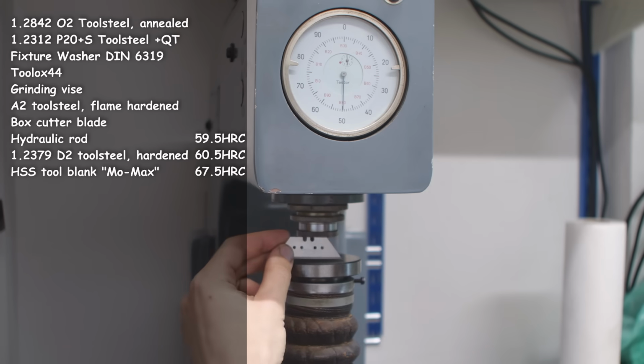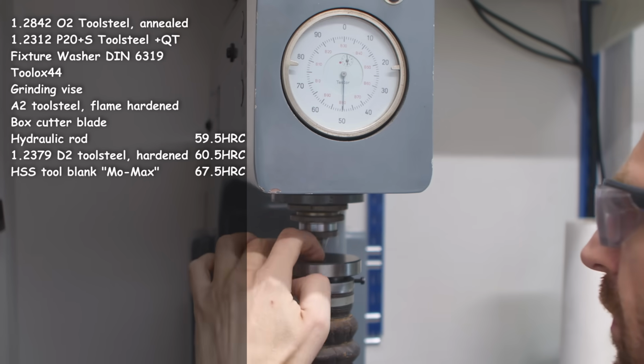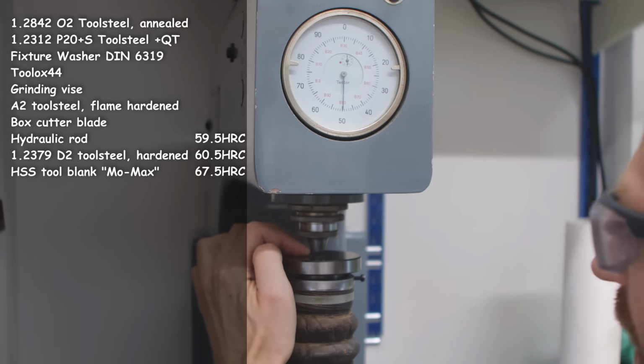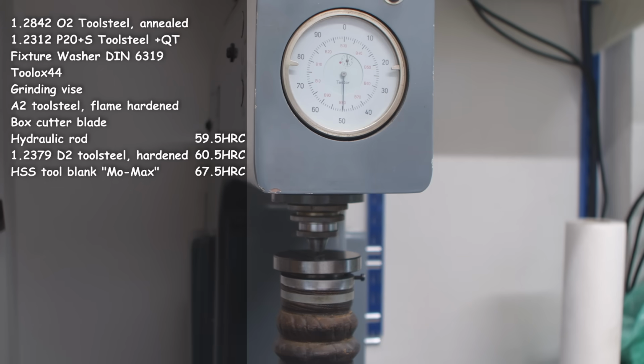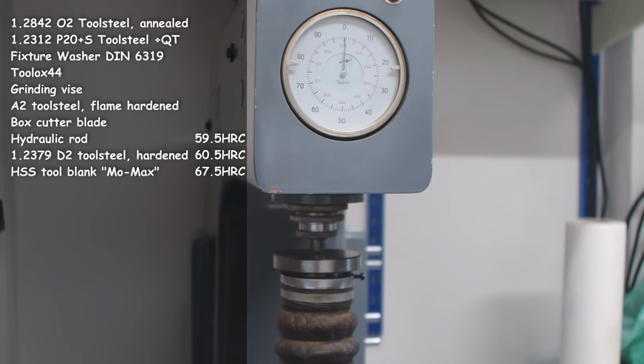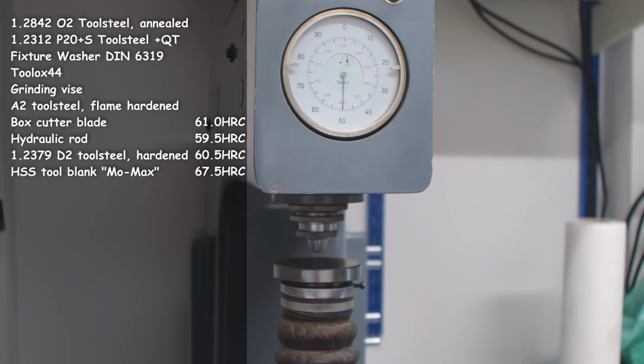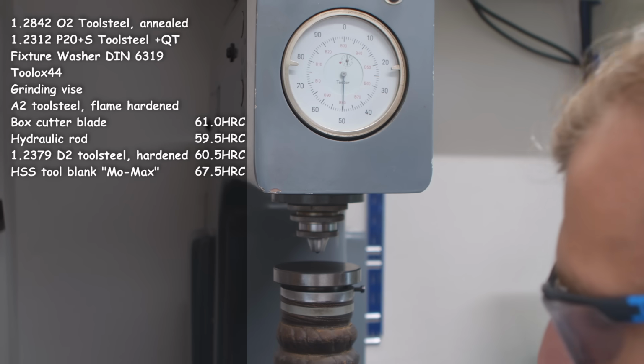So now, box cutter blade. This is relatively thin, and I would consider this the thinnest piece that you can check with a Rockwell C hardness tester, because the diamond will otherwise put a dent on the back side of the part, and that will falsify your reading. So dropping weights. But box cutter blades are surprisingly hard. Yeah, the weight has settled out. So we end up at 61 Rockwell C. And that's not bad for a mass-produced cheap item like a box cutter blade.